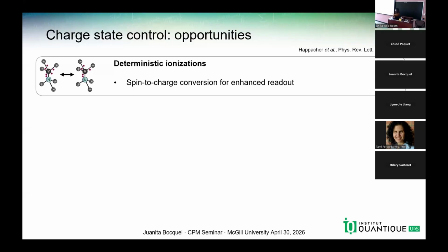What you gain with this is that the photoluminescence from the NV0 versus NV minus is stronger than the spin contrast that you get the way I described it earlier. And by applying a certain window of time, by timing or experimenting in such a way, you are able to take advantage of this difference and have a readout that is more robust.